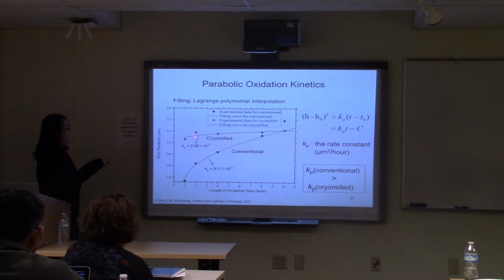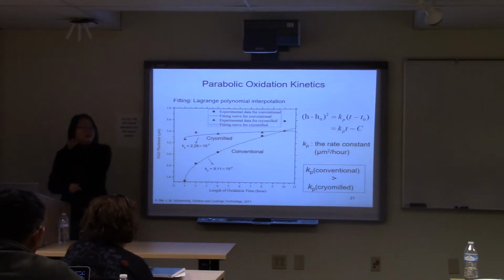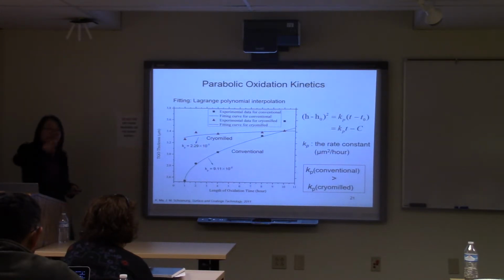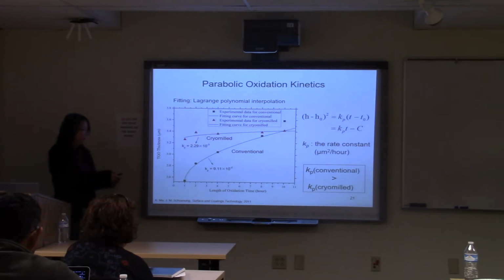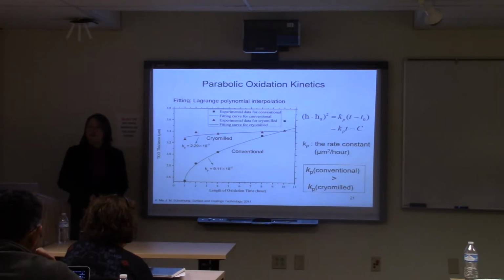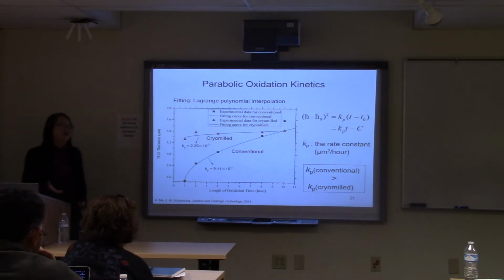So even though the cryomilled coating starts with a thicker TGO layer, I think that's because we introduce a lot of grain boundaries, which provide a faster diffusion path at the beginning. But as time goes by, it's actually very stable, which gives you the longer thermocycling lifetime for this.